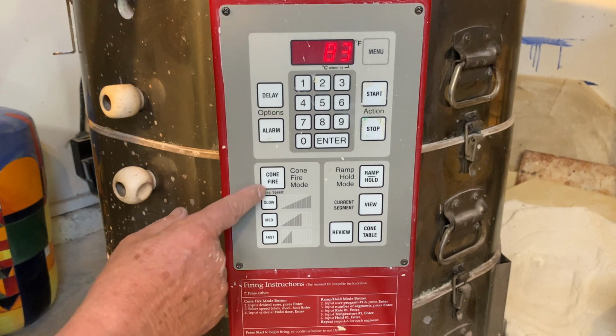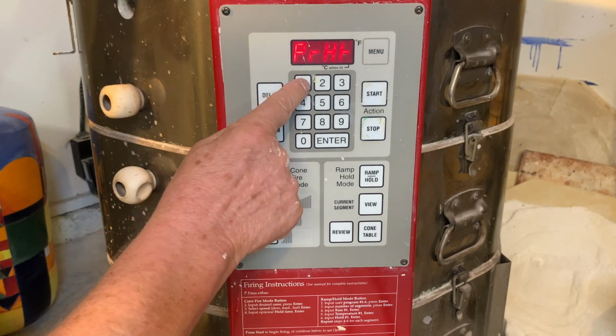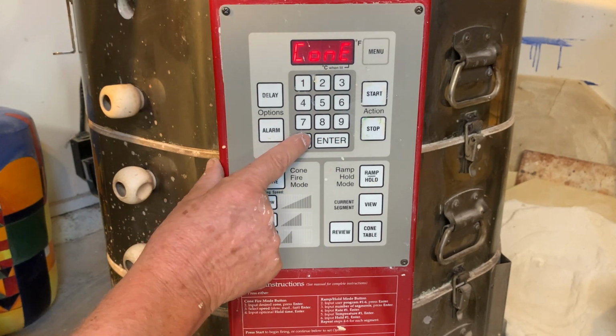All right, the bisque firing I did took 14 hours to get hot. Then it cooled down for another 10 hours or so. And now it's ready to go ahead with my glaze fire. So I'm going to do the same thing I did before. I go to cone fire, and I'm going to preheat it this time just for 10 minutes. And then I'm going to fire it to cone 06 for my glaze.